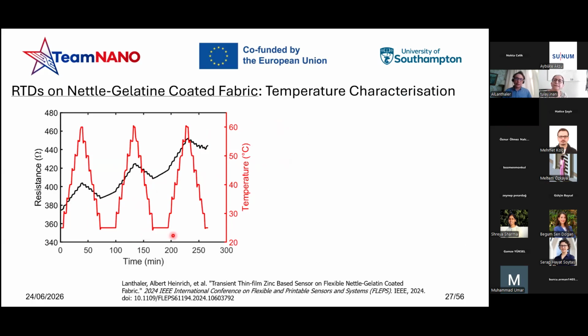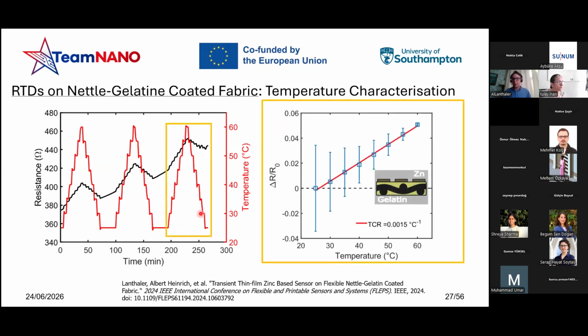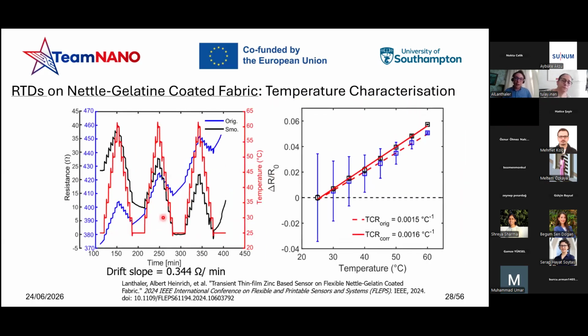So we tested it under temperature conditions, slightly the same as before, from 25 up to 60 degrees Celsius in 5-degree steps, and we were actually able to calibrate it. As you can see over here, there was a drift slope in the output. I'm going to mention and justify that a little bit later. But for now, since it was a constant slope, the idea was basically to subtract the slope from the output and achieve, after mathematical calculus, a stable output in the end.